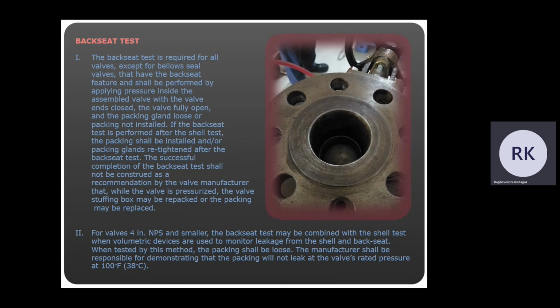For valves 4 inch in nominal pipe size and smaller, the backseat test may be combined with the shell test. When volumetric devices are used to monitor leakage from the shell and the back seat when tested by this method, the packing shall be loose. The manufacturer shall be responsible for demonstrating that the packing will not leak at the valve's rated pressure at 38 degrees.